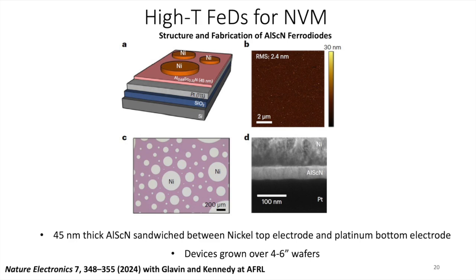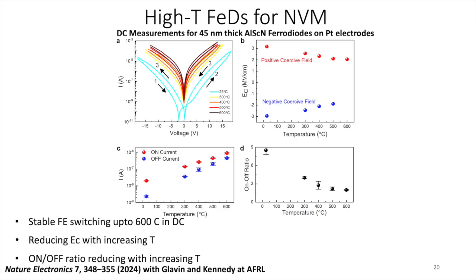The surface roughness and cross-sectional electron micrographs of these devices are shown in figures B and D, for instance. If you go to slide 18, sorry, I've been quoting the numbers wrong because they are a little bit messed up on my slide. On slide 18, you will see the electrical properties of these high temperature ferroelectric diodes, or ferrodiode devices, as we call them. These are DC electrical characteristics. I don't want to go into too much detail, but the 1, 2, 3, 4 that you see in the top right graph tells you the voltage to current sweeps, and you can see that 1 and 2 do not overlap with 3 and 4, right?